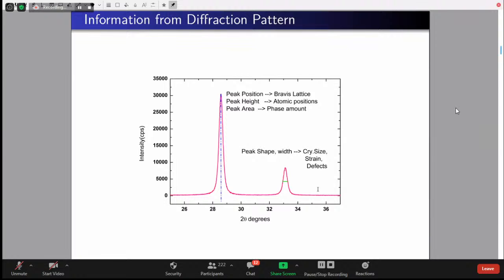But these peaks have shapes, and every shape has a physical interpretation, which has been correlated to the shape of the crystallite, defects or faults in the crystallites, and strain in the crystallites. Everything you can interpret from the shape of these peaks. So from the shape of the peak and its width, we can get crystallite size, strain, and defects. The easiest way is the Scherrer formula, which I am going to show you.